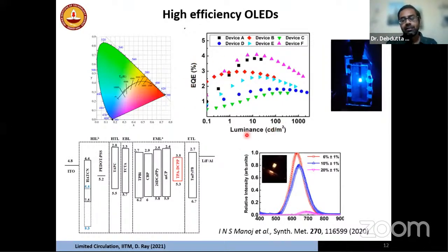So this is efficiency as a function of intensity. So this is called intensity. Typically, your AMOLED screen will have a max intensity of 1000 candelas per meter square. Sometimes this is also called nits. Okay, 1000 nits. You may be operating it at like 200 maybe. You're not operating at the full intensity, but this is the max intensity. You can see that EQE goes down from the max as you go higher and higher.